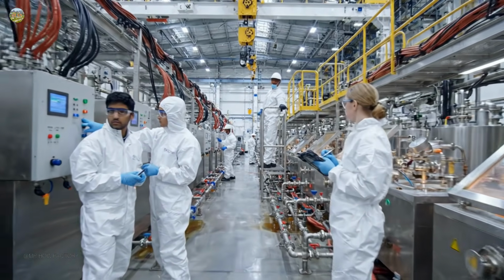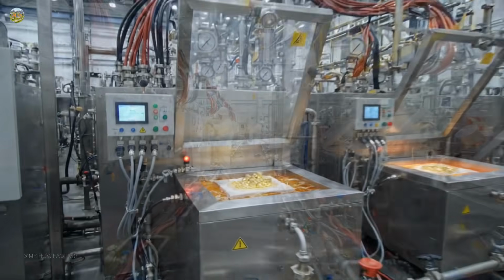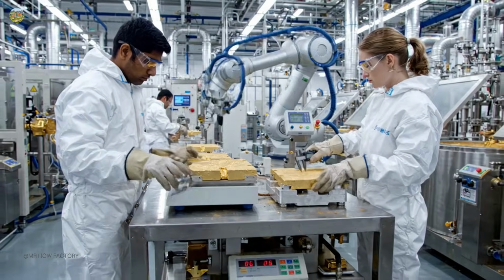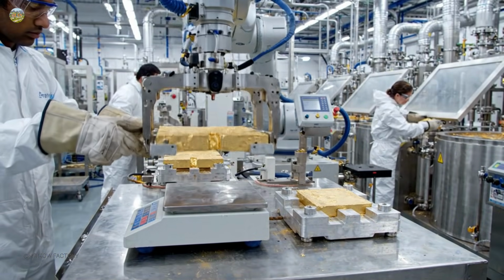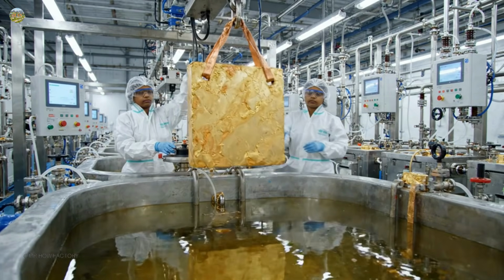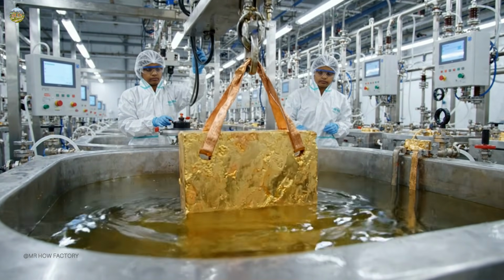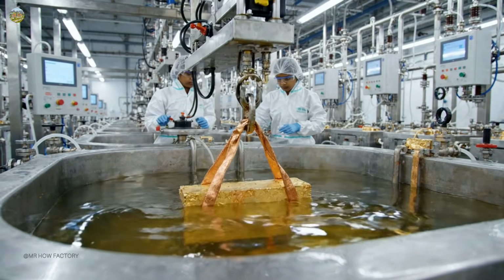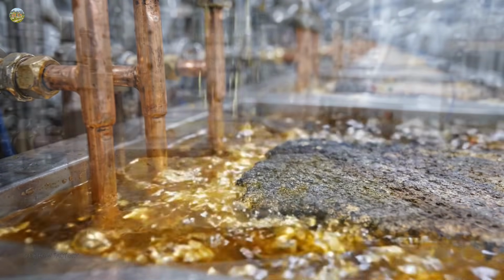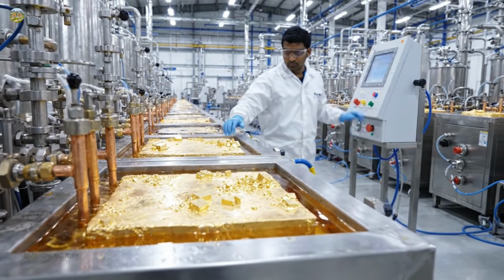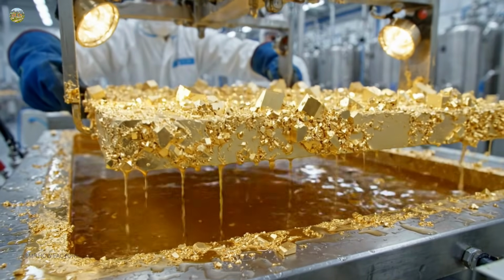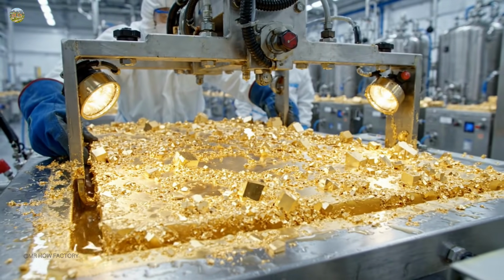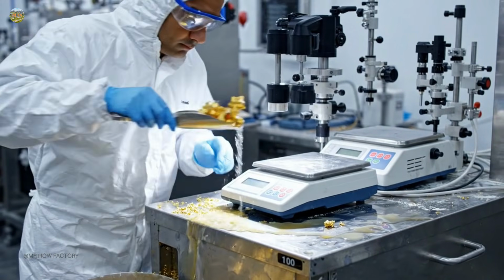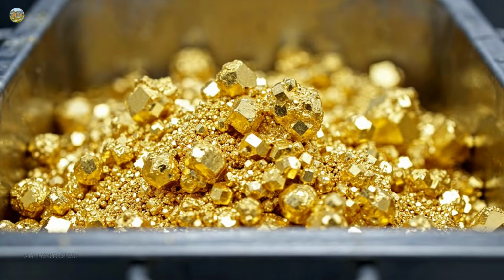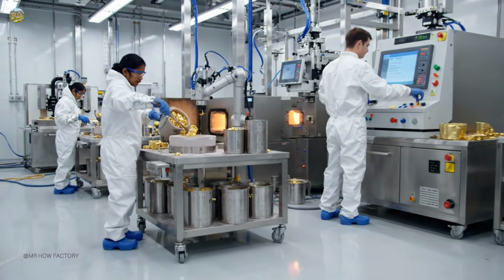For investment gold bars, 99.5% is not pure enough. It must reach 99.99% purity. To do this, refineries use the Wohlwill process. The 99.5% gold is cast into solid plates called anodes and placed into an acid bath. A strong electric current is turned on. Gold dissolves from the plate, moves through the liquid, and deposits onto pure gold sheets at the cathode. All leftover impurities drop to the bottom as waste. What remains are pure gold crystals that are 99.99% pure, fine gold.